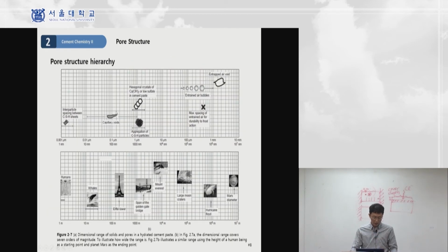Not only do we have calcium silicate hydrate and a different mixture of crystal structures in the given volume, we also have pores. Pores are everywhere in the concrete. In between the calcium silicate hydrate sheets, there's an interparticle pore spacing. This is a pore, an empty region. And there's a capillary void. And also there are entrained air bubbles for special purposes and entrapped air voids. If you can see the scale here, this is nanometer scale, this is micrometer scale, and this is millimeter scale, right? So the crystal structures are intermixed together in a given volume, but also the pores. Pores are everywhere with different scales.